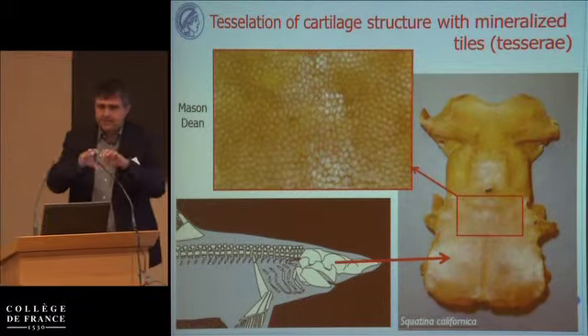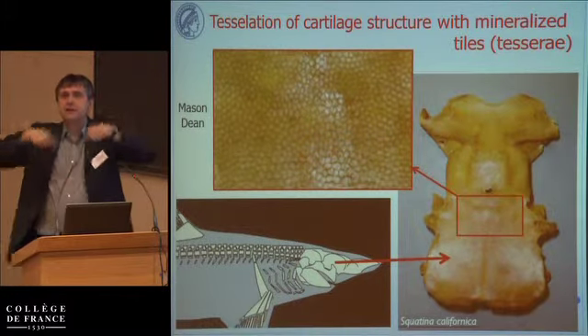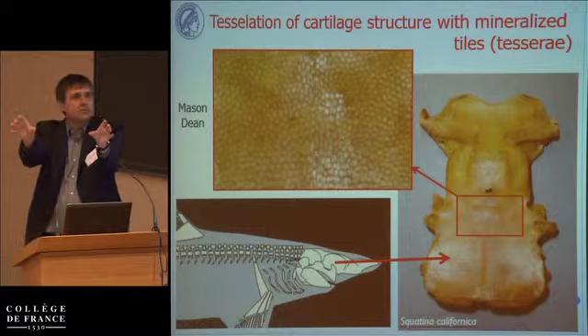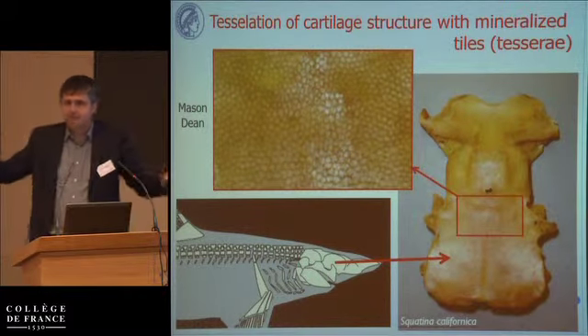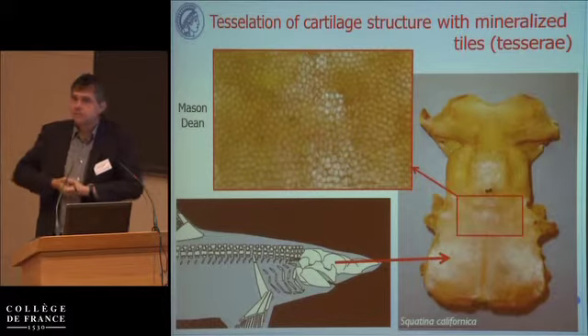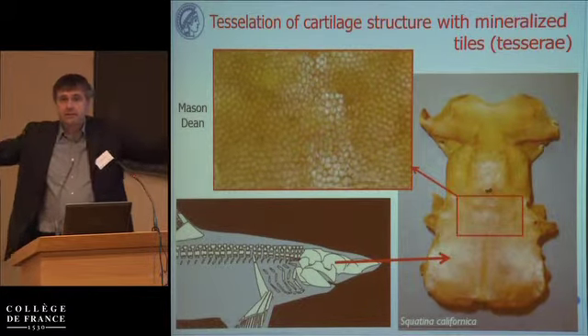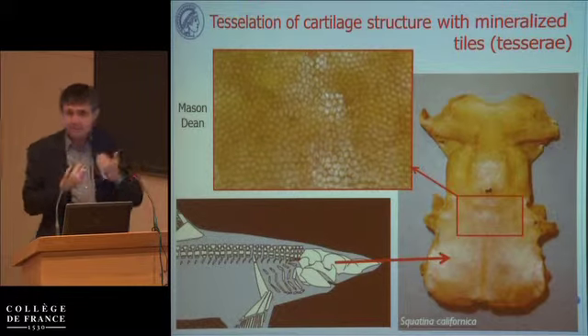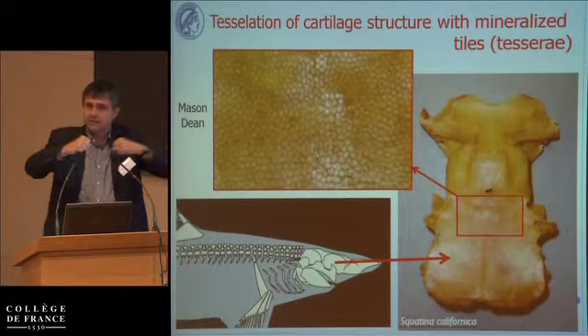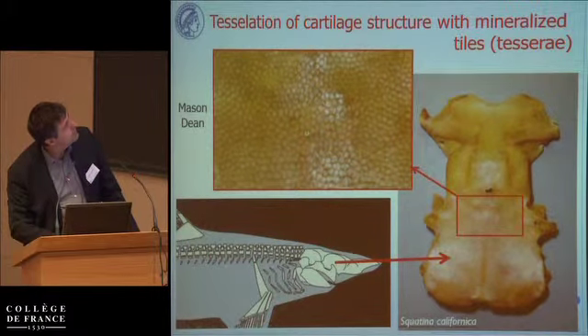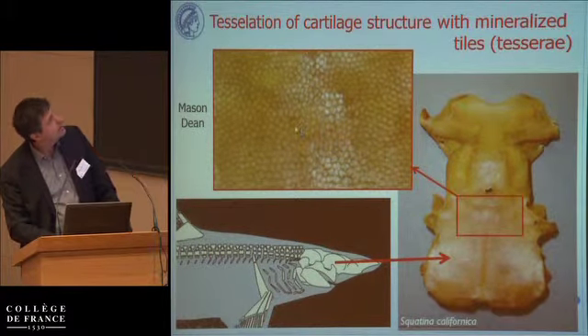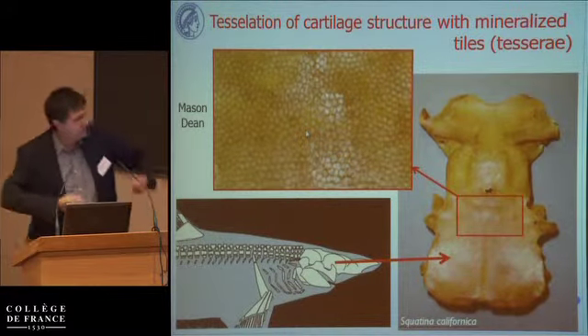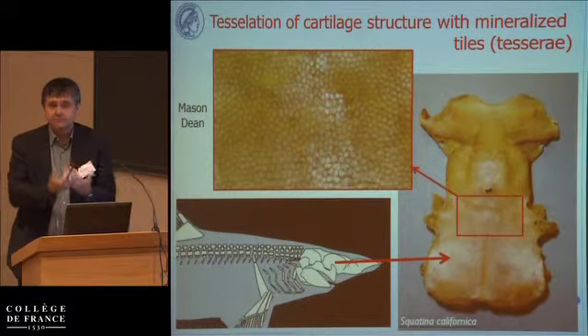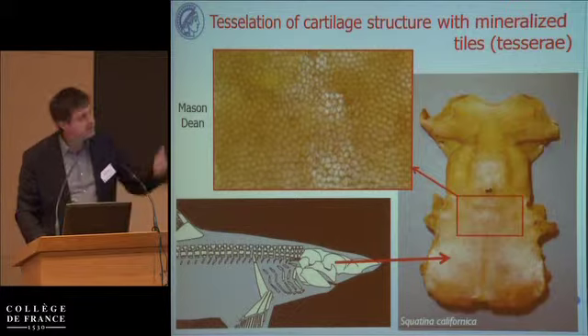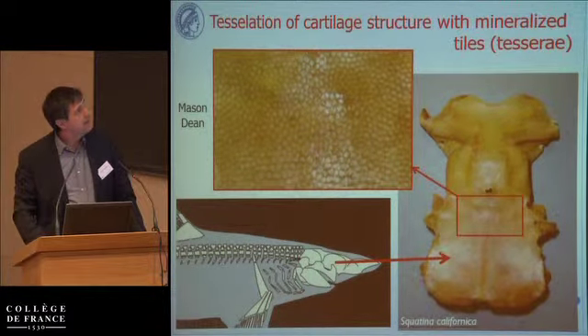Now, just imagine, take a rope of cartilage and put ceramics on top. You wouldn't like to do this because as soon as you bend this, the ceramics will just break and everything is gone. But instead of ceramics, you do what you do in your bathroom. You put tiles. Then you can actually bend, and the same thing happens as with the abrasive-resistant coating: when you're bending on the tensile side, what you're stretching is the soft material in between the tiles, and when you're compressing on the compressive side, the hard tiles bump into each other, and this is what gives you rigidity. So I think the tessellation is absolutely essential in these bones.